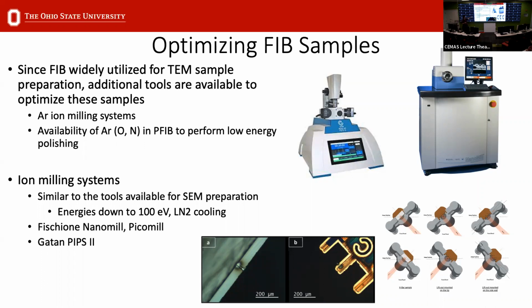In some cases, this other system that I'll talk about a little bit more in a few slides is meant for bulk specimens, for polished specimens, but some have demonstrated that you can also use this to thin down your FIB sample down to energies of 100 eV to remove those damage layers.